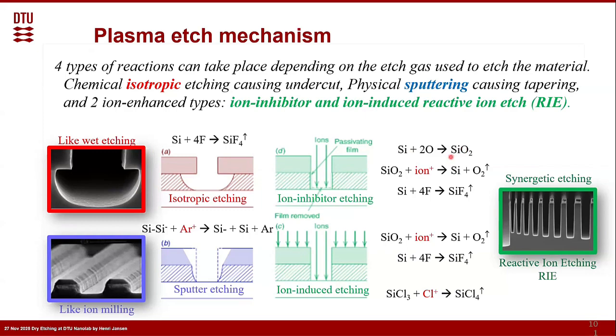But now we add also the ions, which are coming out of our plasma, and we have, let's say, the DC bias, which is controlling it, and the plasma potential, and they are directional. So these ions will then knock out again the oxygen, which is just coming to the surface. It will knock it out again. But it can do that only at the places at the bottom. And the side walls are not seeing the ions, and therefore they are protected by the silicon oxide. At the bottom then, though, it is removed.